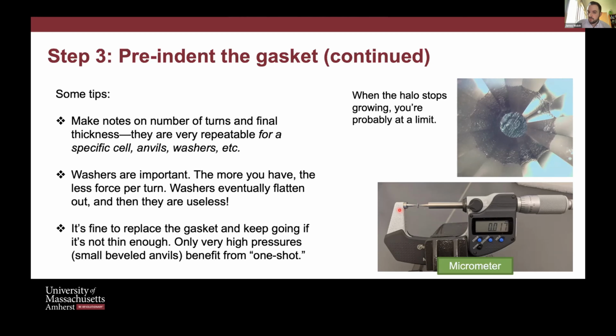There's this misconception, I think, for a lot of people, that you have to do this in one shot, all or nothing. You've got to tighten it as much as you can to the exact right amount, because you don't get to put it back in. You absolutely can put the gasket back in. I think it's important for very, very high pressures, because the repeatability of where the gasket goes, and compressing it and releasing it could cause problems for very high pressure experiments where these minor imperfections can have a bigger effect. So you can imagine, if you don't put the gasket back exactly where it was, now the pavilion faces are not really matching where they used to be. I think it can be an issue for megabar experiments, but for low pressure, absolutely take it out.